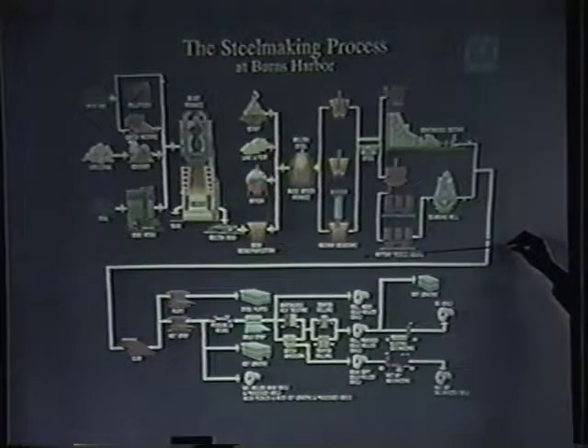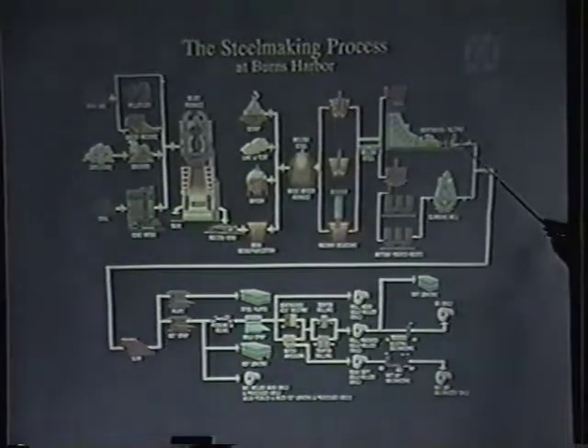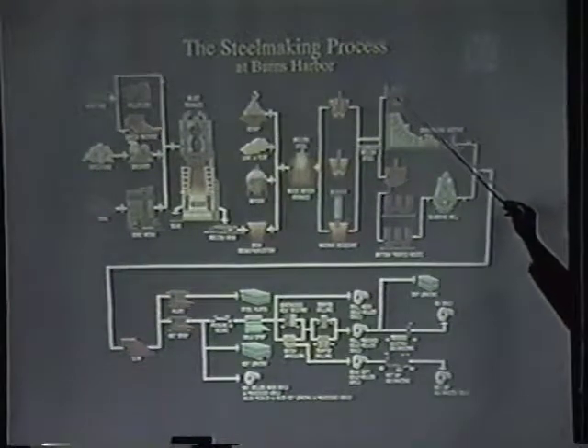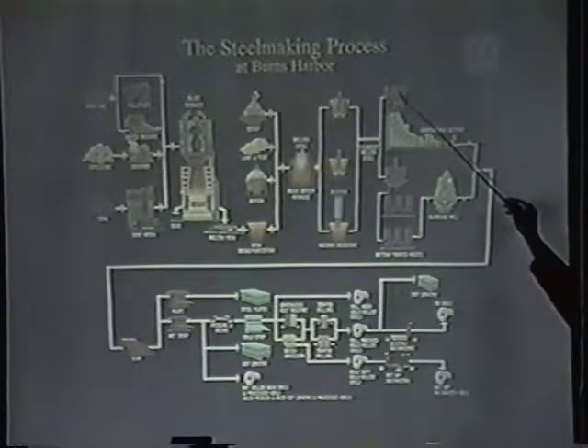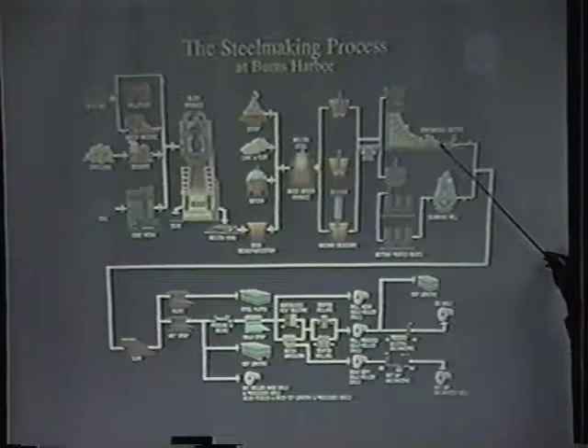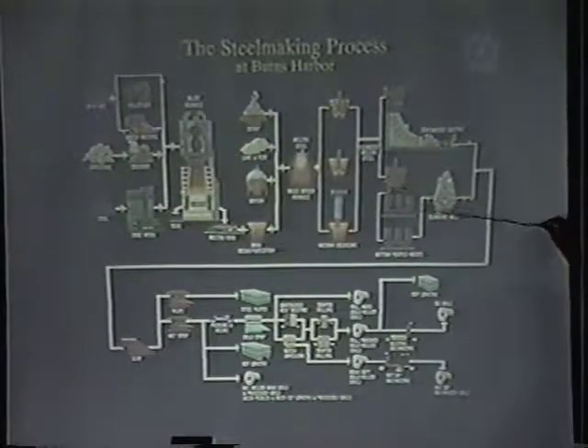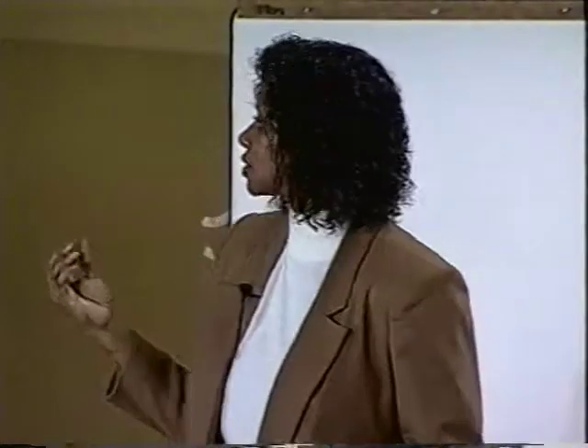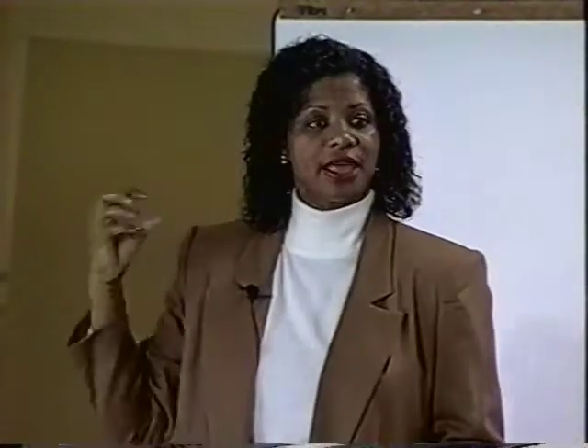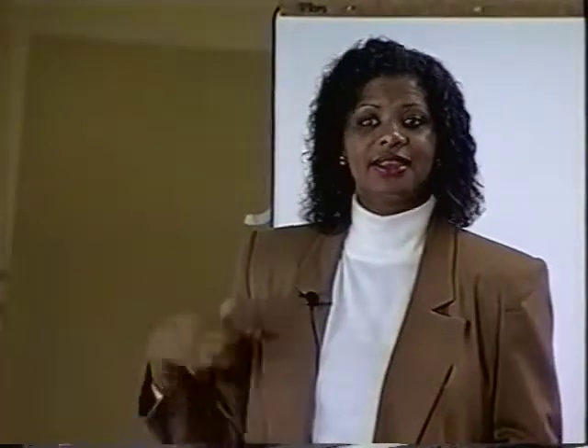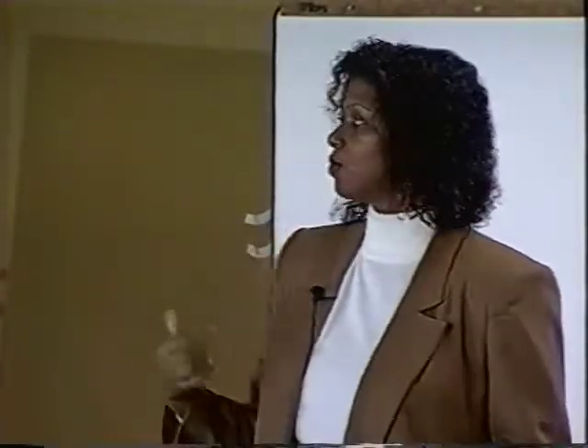You're going to talk about this in this classroom, and then you're going to go out and see all these different operations. And continuous casting takes about a half an hour to convert our liquid steel from the ladle into a slab form. And the ingot teeming method, we're pouring steel into individual molds, allowing that steel to solidify, which can take up to 24 hours and so forth. And then we're stripping that mold away from that steel. You have what's called an ingot. That ingot is then reheated and then rolled into a slab.